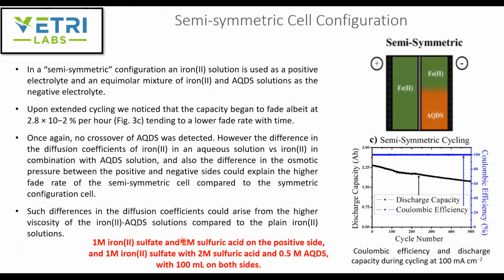Next, the third configuration they took is the semi-symmetric cell configuration. In this, you have a pure iron 2 plus solution on the positive electrolyte, and then you have an equimolar mixture of iron 2 plus and AQDS solution on the negative side. So you have 1 molar iron sulfate and 2 molar sulfuric acid on the positive side, and 1 molar iron sulfate with 2 molar sulfuric acid, and 0.5 molar AQDS on the negative side, and both of them are at